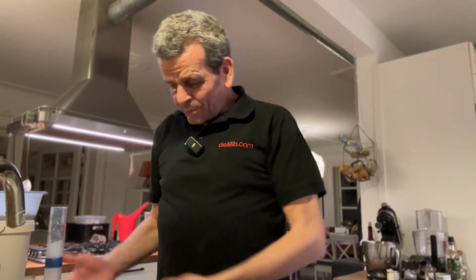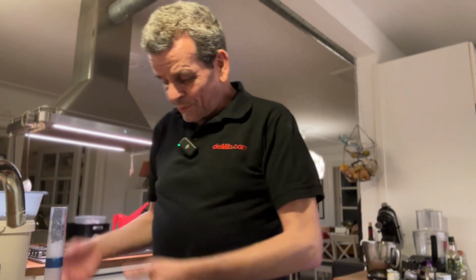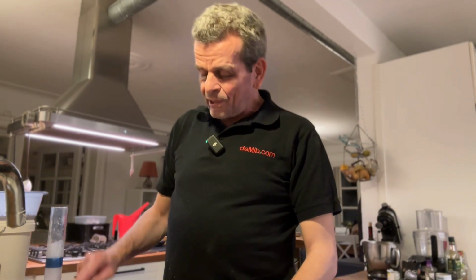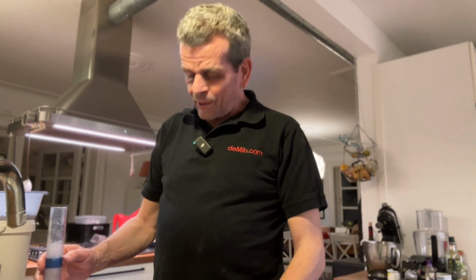reset it to 0. So 0 with the tube. And then you fill up water until it's 100 grams. And then you put a mark. I put a mark where 100 grams of water is. Now we have the scale, so to speak.